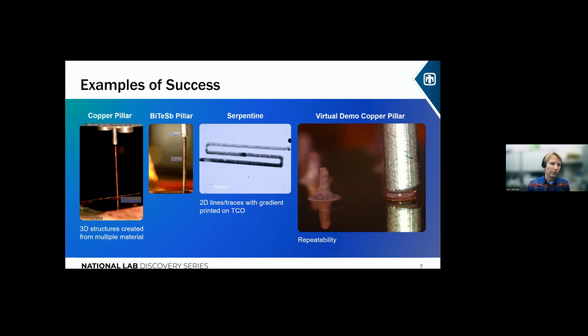And the width was defined by the nozzle print geometry. So it was about 400 microns. Now this 400 microns could be tuned larger, smaller, just depending on the application. However, for the thermoelectric material, we're focused in on that 400 micron to millimeter diameter thermoelectric pillars that was found to be optimal for our particular application.